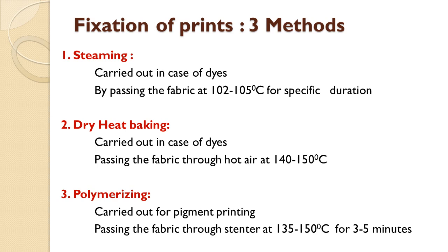Now this duration is dependent on the type of dye. Say we are taking direct dye. Direct dye has higher affinity towards cotton. So to get level print effects, we have to carry out steaming in case of direct dye prints for up to 1 hour. But in case of reactive dyes, the duration is very less, like 8 to 10 minutes, because reactive dye fixation will occur very fast. So the duration required for reactive dyes is 8 to 10 minutes.